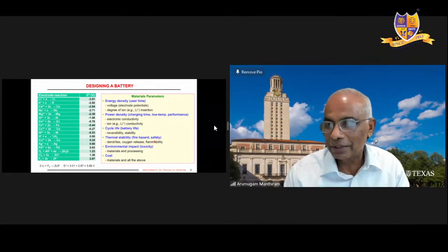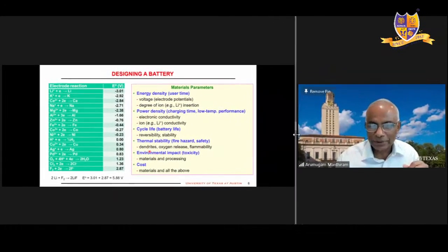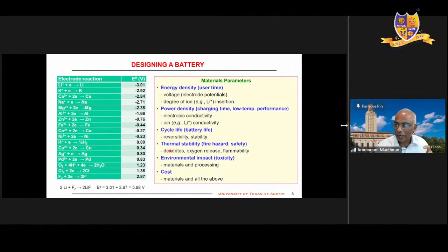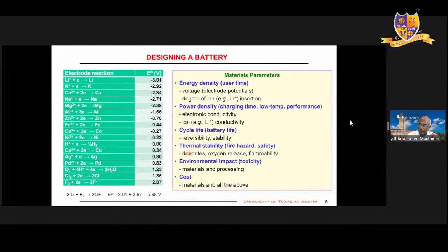But who is starting it? The one who initiates is the graphite anode. If you charge fast, instead of lithium going inside, it will deposit on the surface. Unfortunately, when it deposits, it does not deposit smoothly. It deposits like a needle. That's called a dendrite. Once you have a needle like that, it will make a hole in the separator. Then it will internally connect the anode to the cathode. So the electrons will not flow through the external circuit. They will be flowing internally. Current flows internally, heat, temperature goes up.